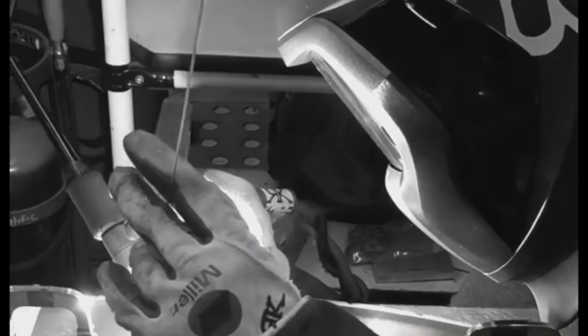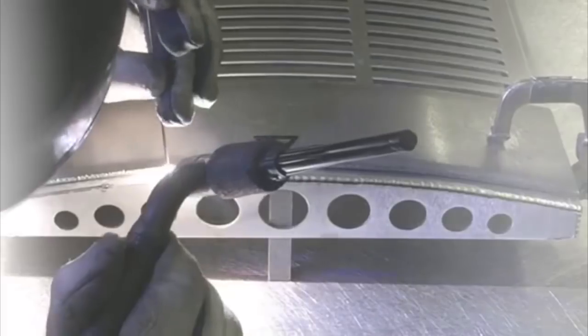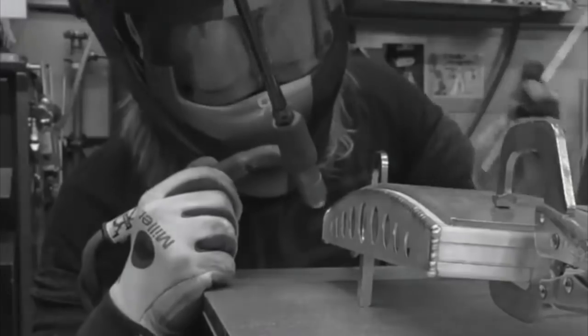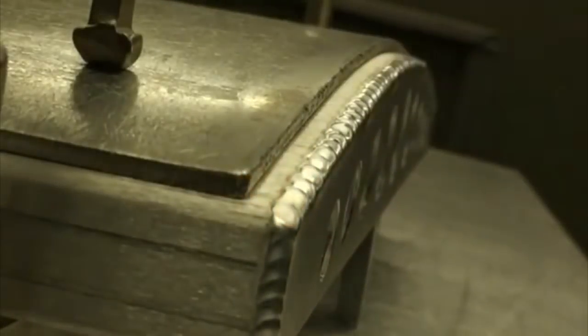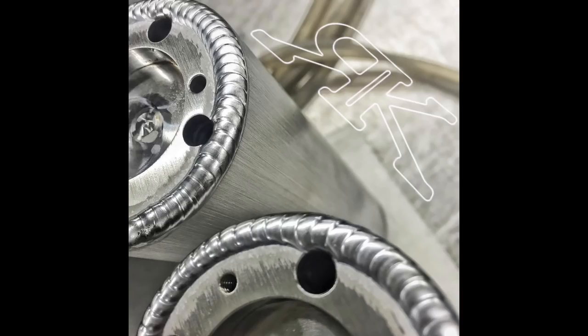And aluminum, it's guys that do a lot of testing to prove out procedures. They know that it's always a battle between maintaining mechanical properties and porosity. It's always a balance. You've got to get an acceptable amount of porosity, which hopefully is none, but sometimes there's some slight amount allowed depending on the application or the code, but then mechanical properties come in.